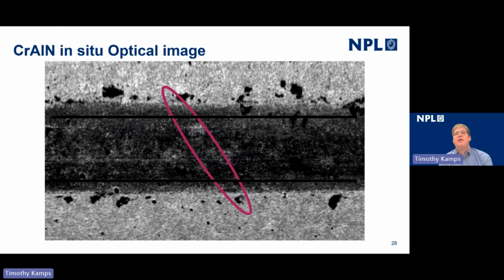And when we look at the friction signal that's been spatially resolved against this, what we notice is that the transient friction signal only exists for a very short number of passes after the initial failure of the coating. And this makes it very difficult to identify using conventional temporal techniques where we're acquiring the data without any spatial information that the change in friction signal that we've seen is actually attributed to the removal of the coating. Yet when we use a technique where we've recorded the images and the friction signal in a way that we can rewind the data and look back at it, we can actually identify this location on the disk and see that the failure has occurred there and what the friction response is.